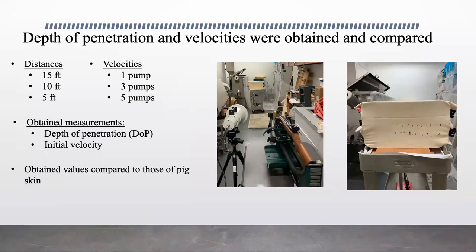In my project, I conducted a series of shooting tests to study how the chamois affects how much a pellet penetrates the gelatin when fired from an air rifle. Since firearms are often used at long distances, the distance between the muzzle and the gel were altered to see the chamois effectiveness at different distances. Different velocities were also employed. Velocities were recorded using an instrument called the Doppler radar, capable of tracking a projectile as it travels through the air. Obtained values consisted of how far a pellet penetrated the gel — known as depth of penetration or DOP — and the pellet's initial velocity.